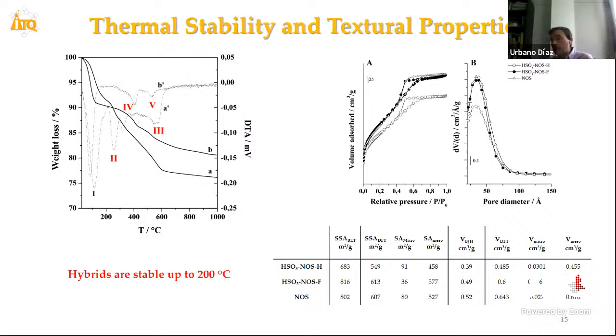The characterization of these hybrid materials is performed, being appreciated from TGA that the stability of the materials is possible to identify up to 200 degrees. The isotherms of the materials are the classical type 4 isotherm, characteristic of mesoporous material, with a pore size distribution around 40-50 Angstrom, and in general the surface area and the total volume obtained are in the range of the standard of mesoporous materials.